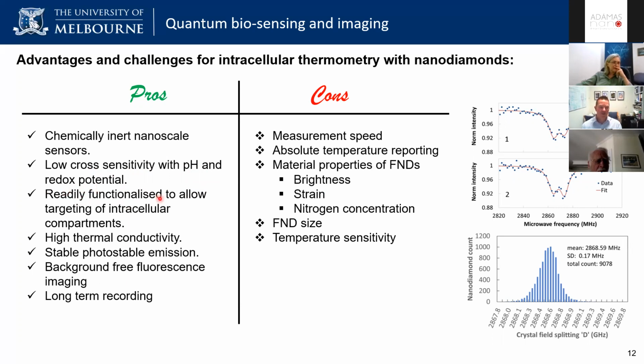We can readily functionalize the diamond to get them to interesting compartments and start to probe temperature in different parts of the cell, which is really good. Diamond has a really high thermal conductivity, so it's able to directly report temperature changes very effectively. It's got a stable emission, which means that we can track it for a really long time. So these are all the wonderful things about diamond.